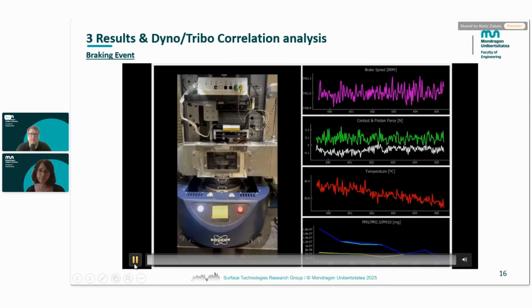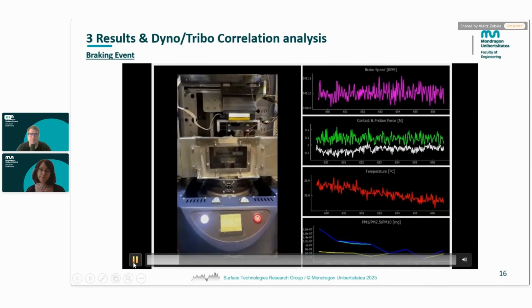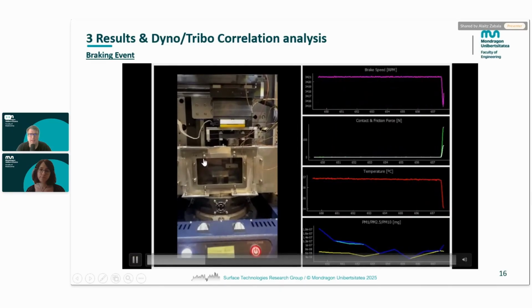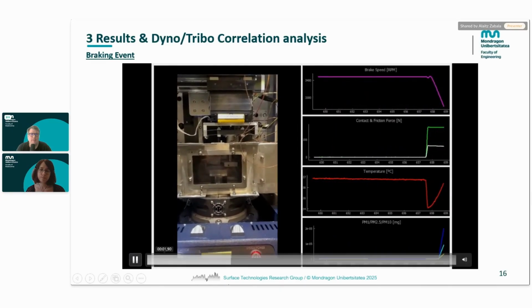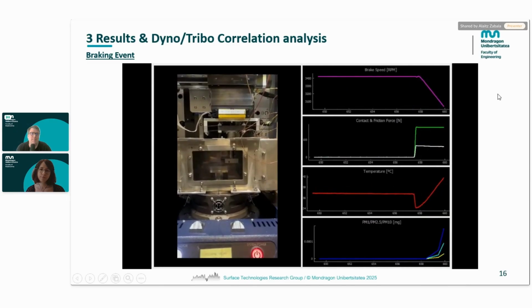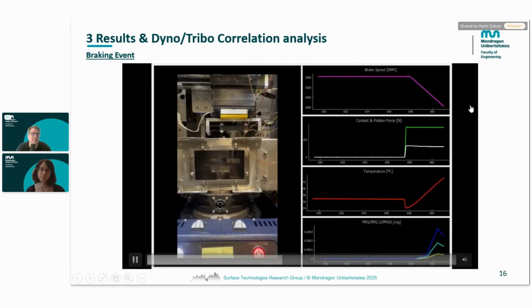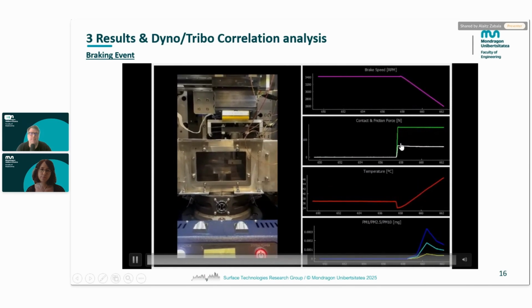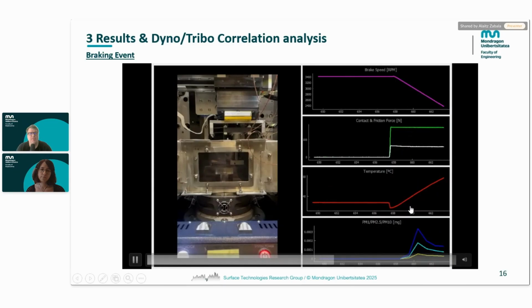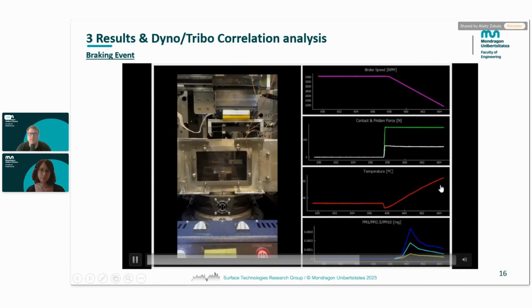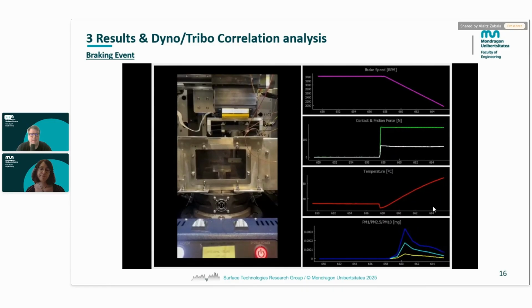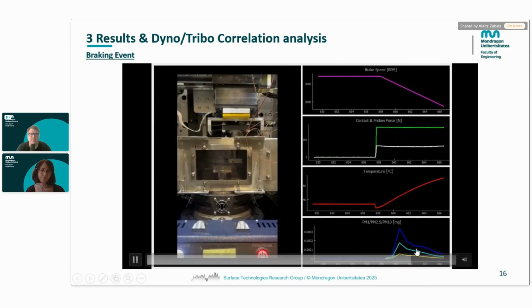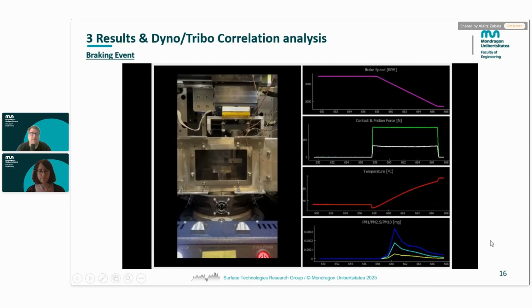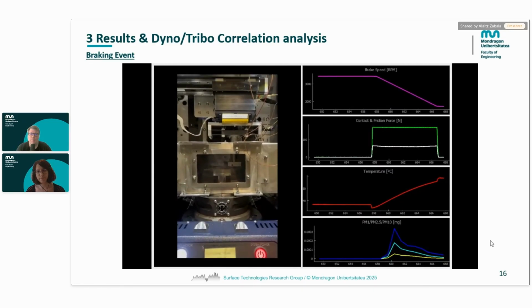So here you can see a simulation of the braking event, and I want to focus on the actuator of the Tribolab. There you can see that we applied a normal force, and then we can monitor the decrease of the brake speed, the evolution of the contact force and the friction force, and the rise of the temperature due to the energy that we introduce to the system. And finally, we can also see the particle emission that happens during the braking. Okay, this is only for one braking. And then we can analyze the braking metrics in the next slide.